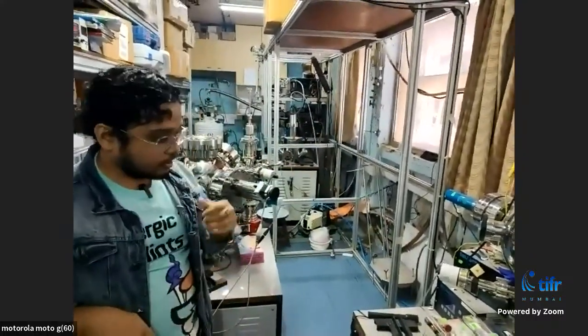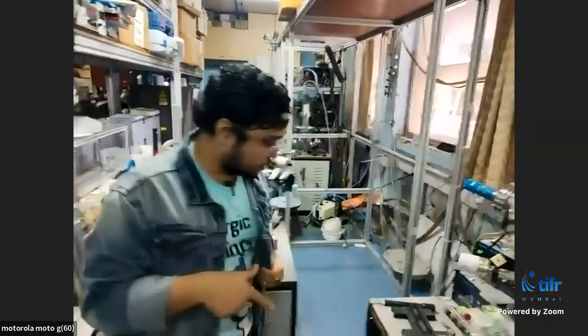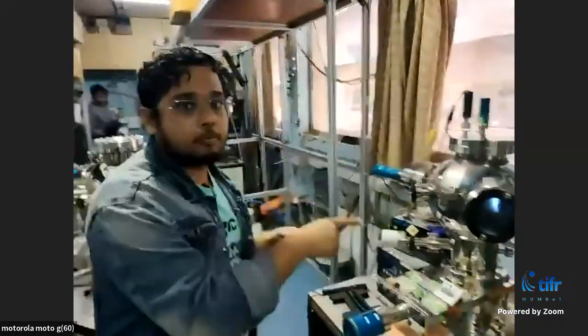So here you can start the process, and you can see the plasma of the superconducting material niobium, because here we have installed the niobium. Okay, so yeah. It is the blue plasma we are seeing. It is the plasma of the niobium. So there is a shutter. We just open the shutter, and you can see that is the position of the substrate. So here we can place a substrate, and this plasma goes from this side to this side and is deposited on the substrate, and we get a thin film.